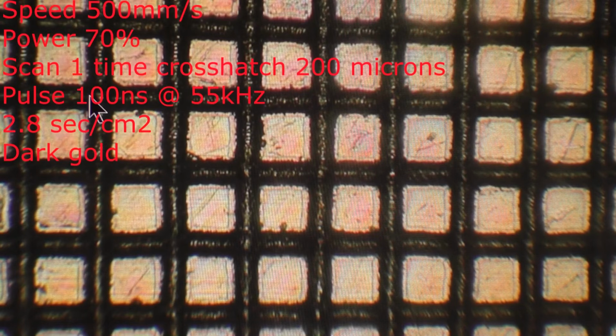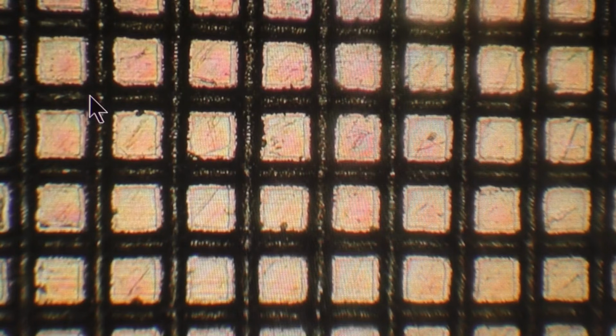And in between that grid, we've created a heating effect on the surface. Now, if you look at the colour of each one of those squares, you'll see that what we've actually done, we've created a flat, thin film interference pattern on each one of those. We've created a colour, which is pink, yellowy, whatever it is, it hits the eye as a sparkly gold. And it's viewable from all sorts of directions. And I think that's purely because we've exploited the principle that we started off thinking about, which is a cellular structure. Although they're nanocell structures on a butterfly wing, these are bigger, but they're exploiting the same effect.